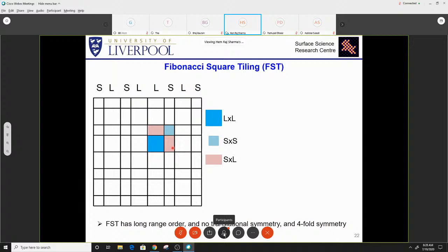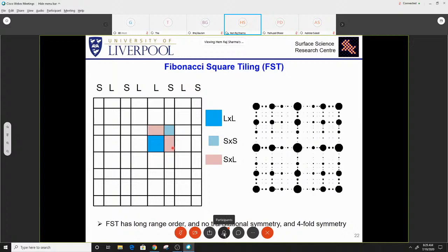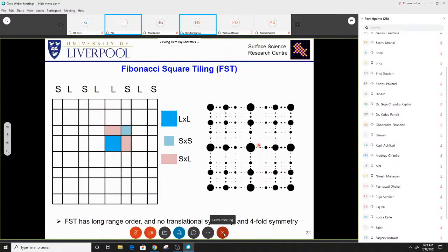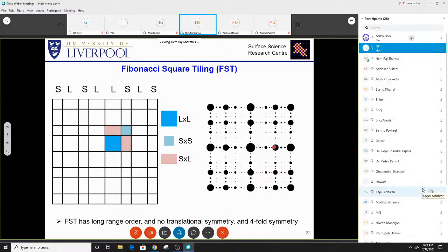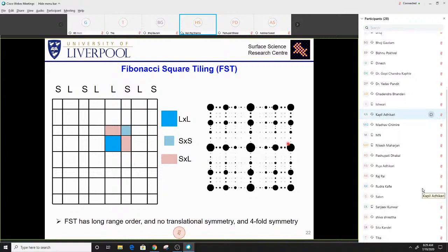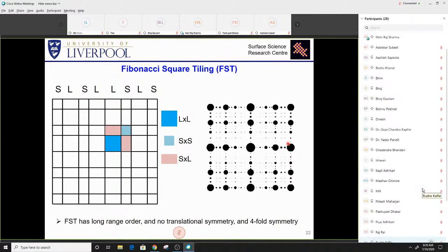That means that it has symmetry. There are different ways to check your symmetry. You can do it experimentally, with diffraction, or in theory, you can do the Fourier transform. The points are not distributed in a periodic order. They are distributed quasiperiodically. So we basically measure this distance and that distance. So let's see how we obtain the distance.